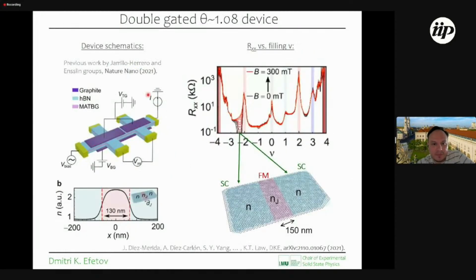And so, right, these are the devices which we made. These devices consist of top gates, graphite and a graphite backgate, whereas in the center you see the magic angle graphene. And what we can do is we can now locally change the density in these devices, and we can basically create devices where the density in a local region of around 130 nanometers, which is defined by the slit, is different from the density everywhere else in the device.